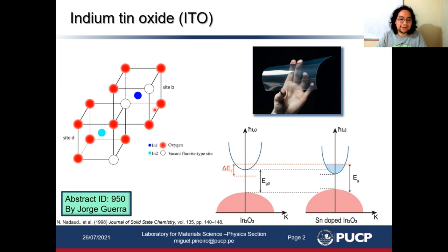This degeneracy is caused by substitutional tin atoms that occupy indium sites. This affects distortion of the crystal structure and leads to formation of oxygen vacancies. These defects—substitutional tin and oxygen vacancies—contribute charge carriers to the conduction band and explain the good conductivity. Due to these properties, they are used in display devices, but these properties are affected by complicated microstructure created during film deposition and post-deposition annealing.